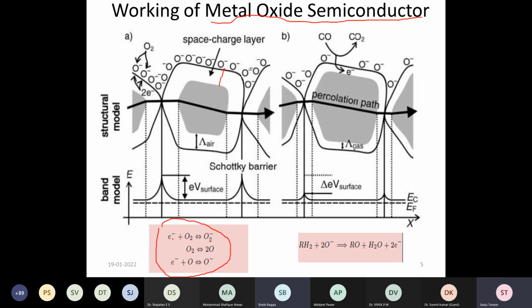This oxygen will come into contact with this electron and charge it. So there is a deficiency of electrons, due to which the Schottky barrier height is increased. We can see it over here. These are the grain boundaries, grain to grain. The barriers work as a barrier for the flow of electrons from one grain to another grain. On the boundaries we can see the barrier height is increasing because oxygen is reacting with these electrons.